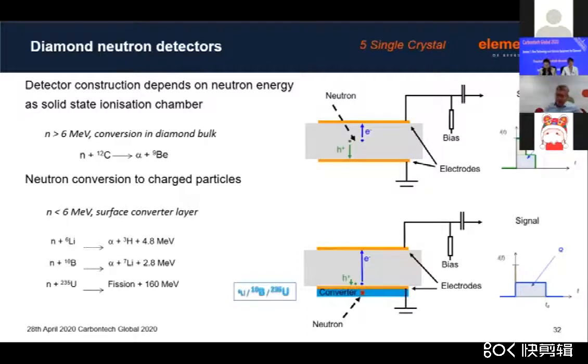Oh, yeah, so what I mean by a converter layer in these materials is where you add a layer that will absorb neutrons and then actually translate that into an alpha particle. And you do this when the energy of the neutron is so low that it would normally just pass straight through the diamond without it being detected. So essentially what you're doing is, if you put, say, a lithium layer on here, when the neutron encounters the lithium-6 ion, it actually produces an alpha particle, which then passes into the diamond, and you're then able to measure the response of that alpha particle. But because you know the characteristics of the converter layer, you can then translate that into the actual properties of the neutron itself. Hopefully that answers the question.